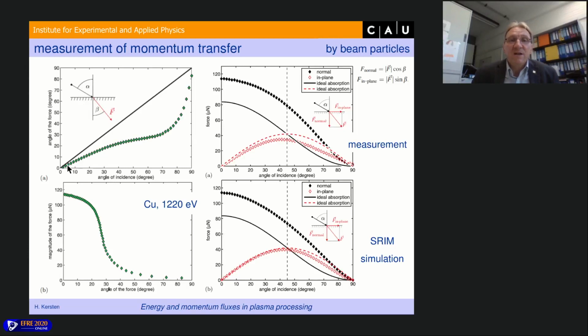And if all incoming ions would stick at the substrate or at the probe, then we would have this line. But the measurement is below this line, as you can see. And why? Because there is sputtering. There is an additional loss of momentum due to sputtering. So that means if all particles stick, then we have a momentum transfer factor of 1. If all particles would be reflected, then we have a momentum transfer factor of 2. So in reality, it is in between. Due to sputtering and reflection, we have a factor in between.